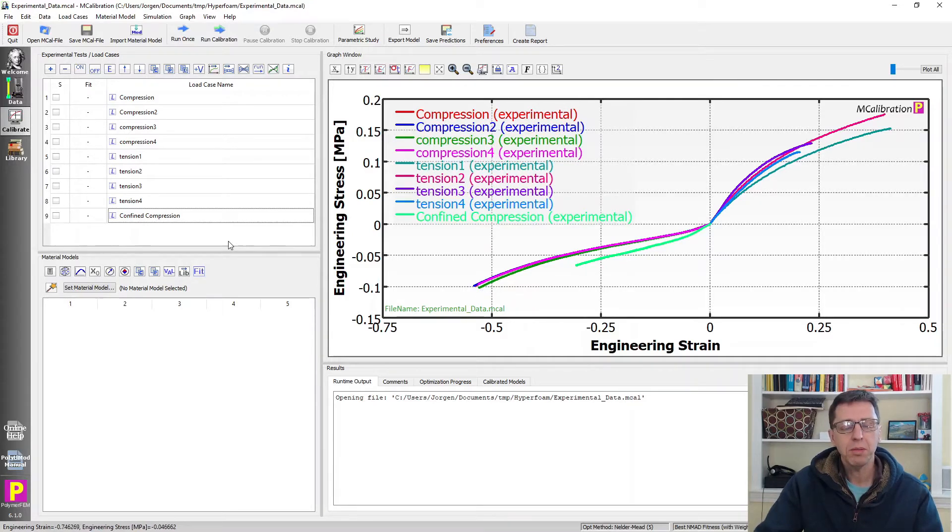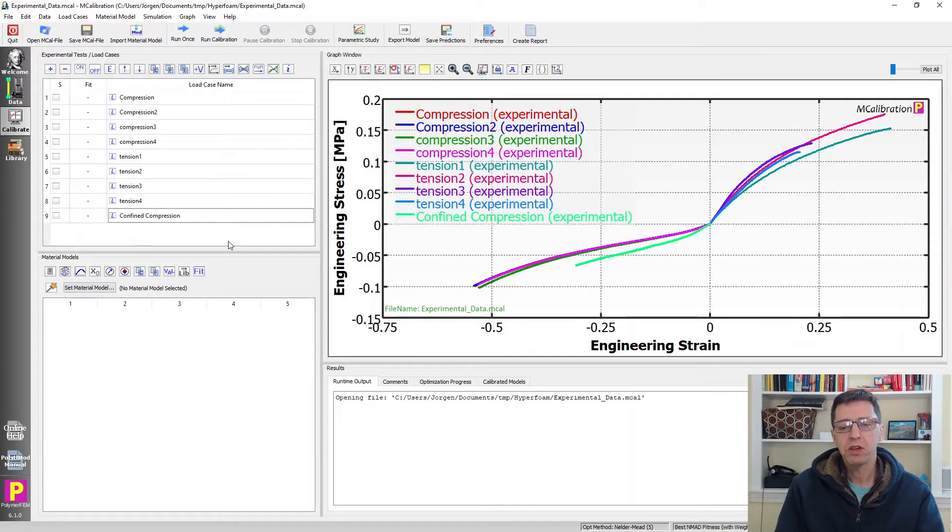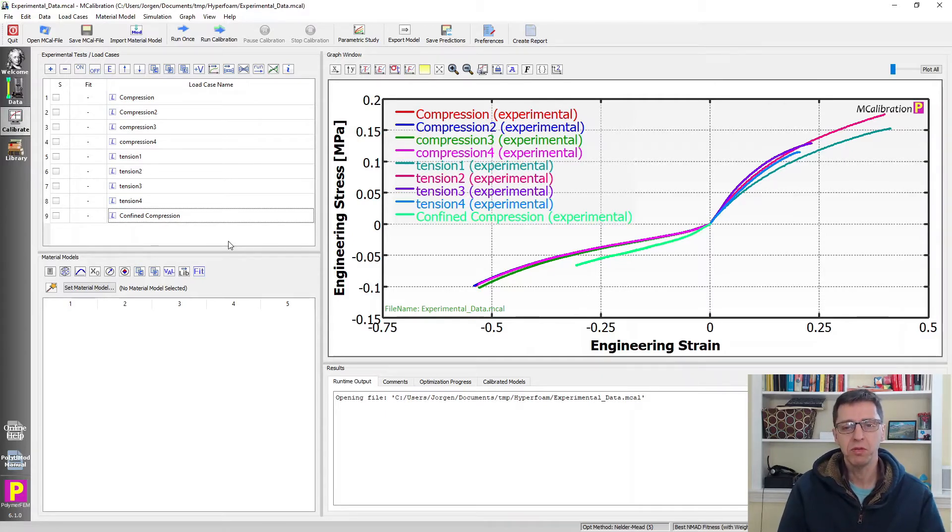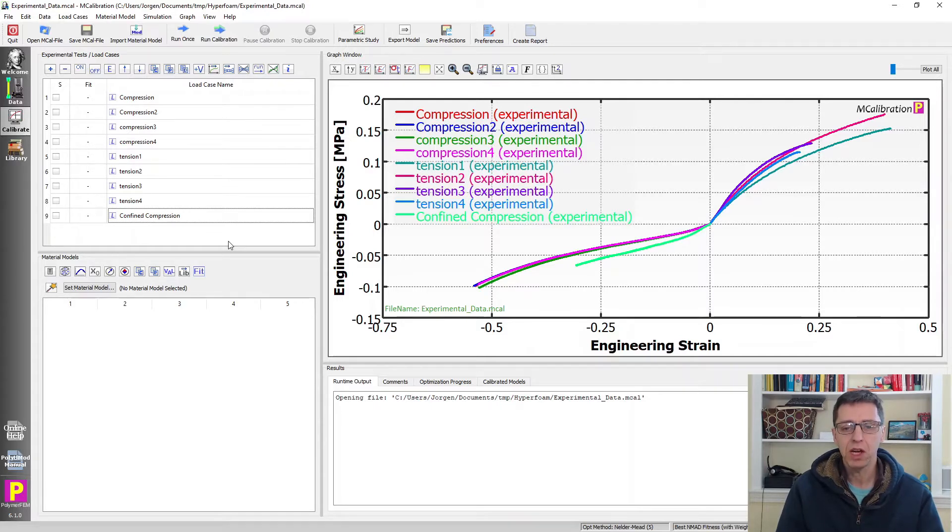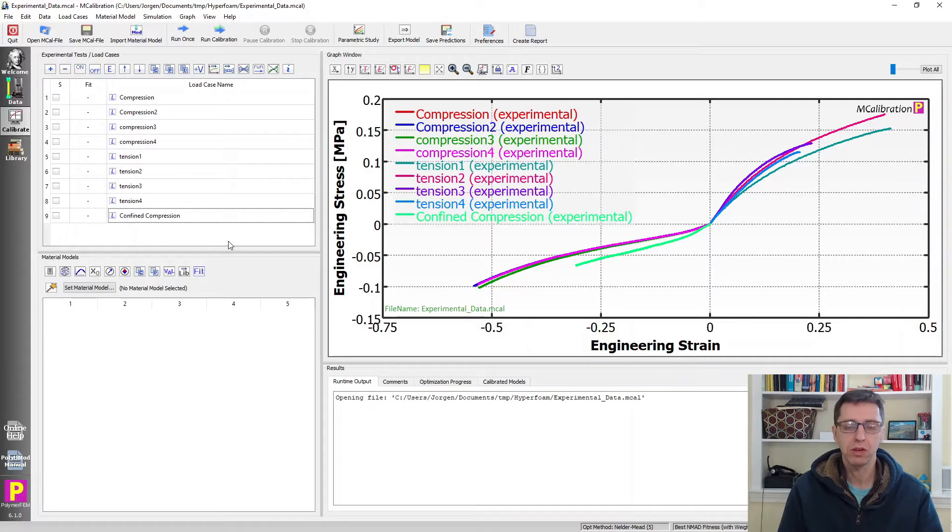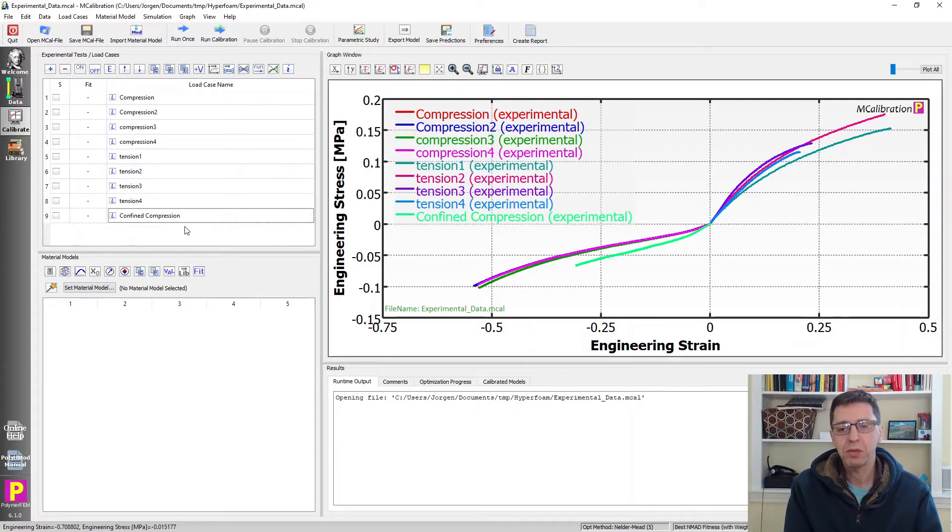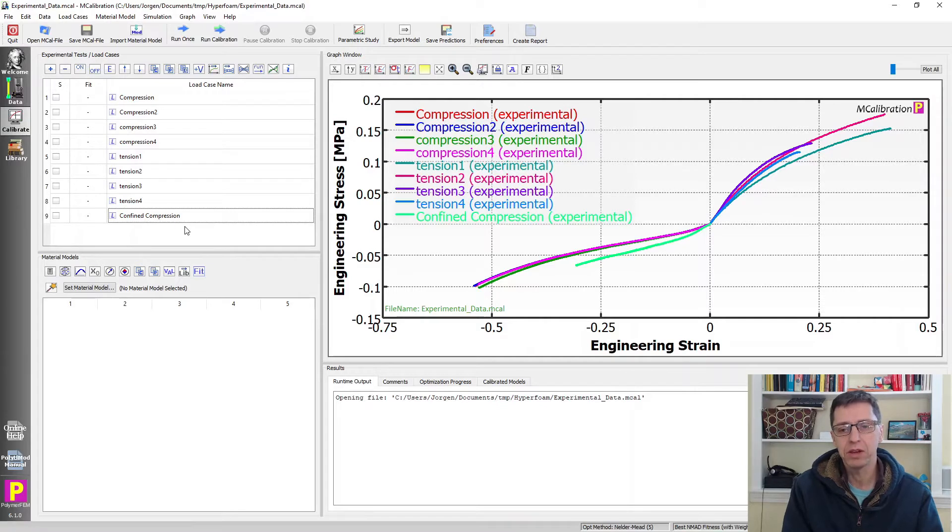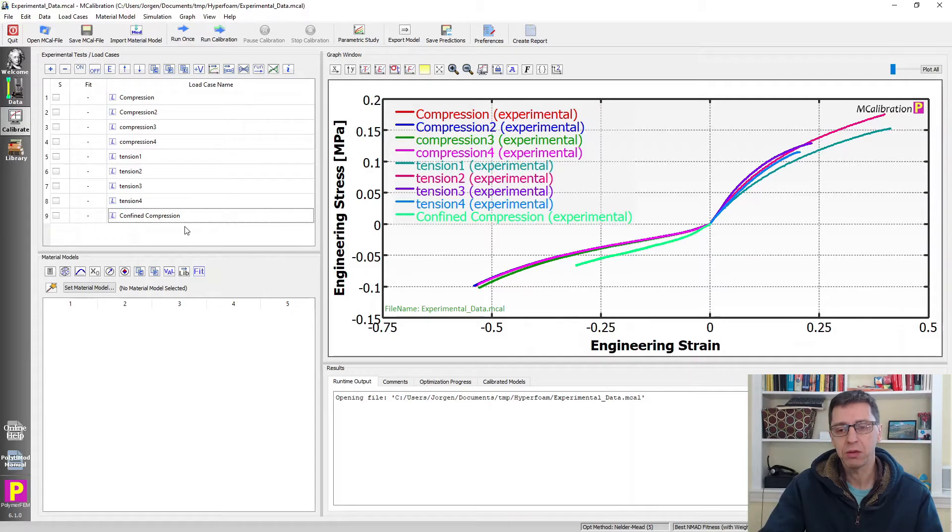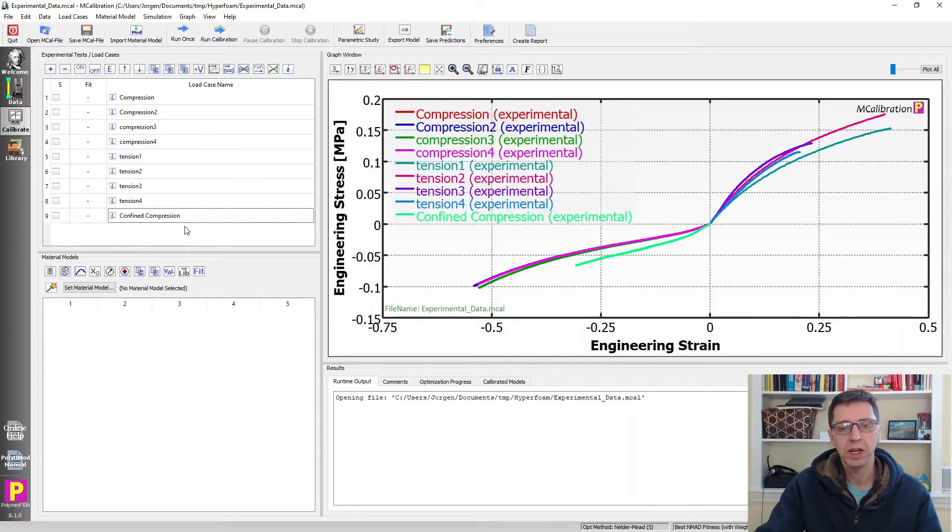The other thing when you should think about when you look at foam data like this, or any data for any material for that matter, is: is this enough data to calibrate one of these hyperfoam type material models? A hyperfoam model is based basically on the Ogden energy function, perhaps you're more familiar with that. And the rule of thumb is you need to have at least two, preferably three different loading modes of data in order to calibrate the model. Otherwise you will not have a unique set of parameters. So here we have uniaxial tension, compression, confined compression. So one could argue that this is perhaps the minimum number of tests that you need for calibrating such a model. I would prefer if I also had either shear or biaxial loading on this foam as well, because I think that would be even better. But say this is what we have, and we're going to try to work with this data.